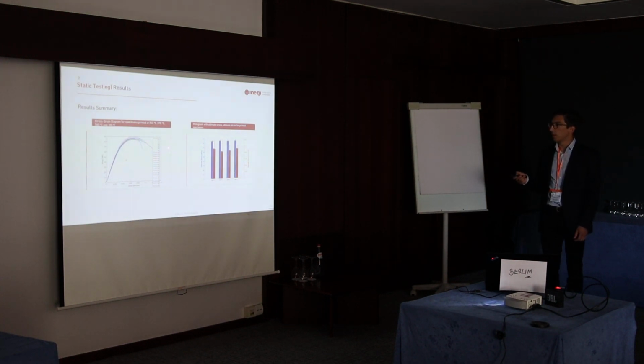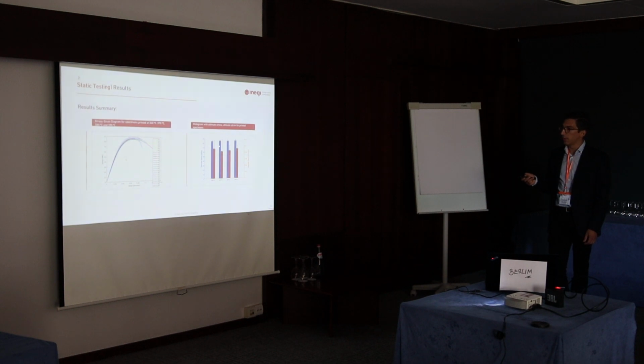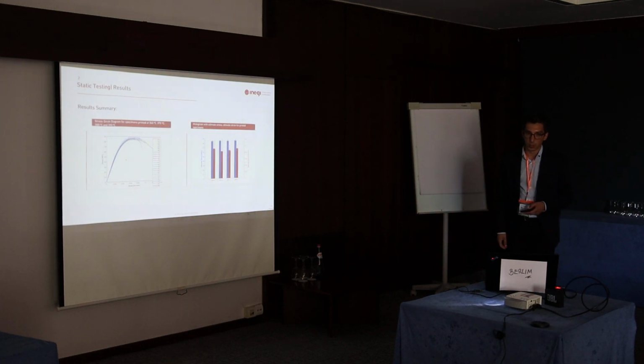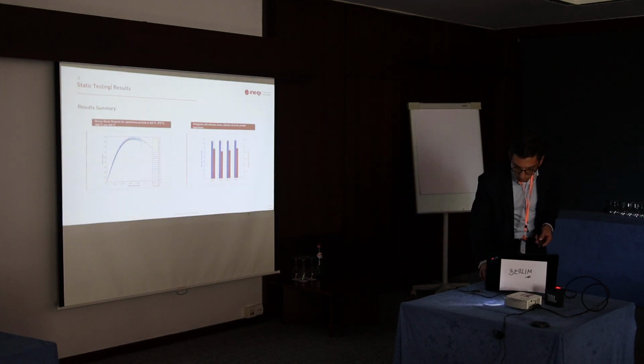But you can see here that the major finding that we find is that a slight increase in temperature produces a slight increase in ultimate stress, and it produces a more stable ultimate strain. So in this case, you have here these error bars that are decreasing, especially in terms of strain when the temperature goes up. So we believe this to be a good result.